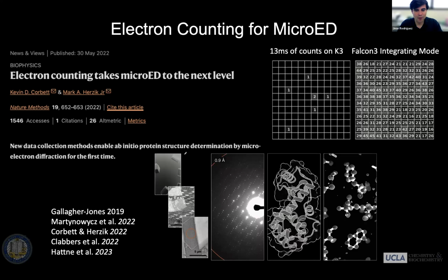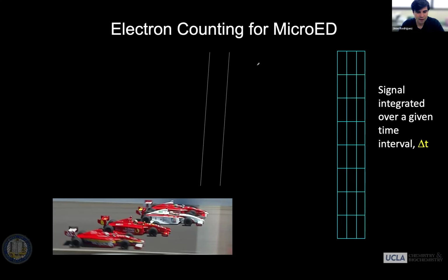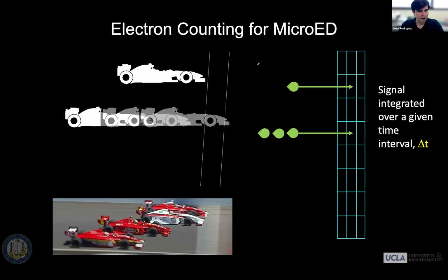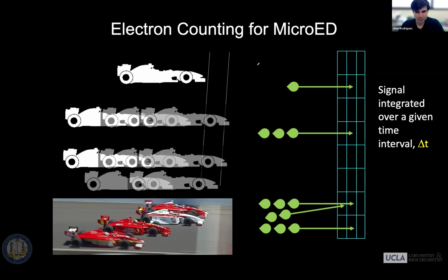And the idea for coincidence loss is simple. We're trying to overcome the issue that these detectors count with a finite rate and aren't necessarily able to discriminate individual events in a single pixel if those events coincide with other events in neighboring pixels or in the same pixel at the same time. Thinking about a race car analogy, it's easy to tell whether a race car is crossing the finish line if it is the only one crossing at that time and you can discriminate it cleanly. But if several cars cross the finish line at the same time in the same lane, it becomes difficult to know how many you could count. And if a whole swath of them come together and are very closely matched, it becomes rather difficult to count them all individually. And so you tend to undercount.